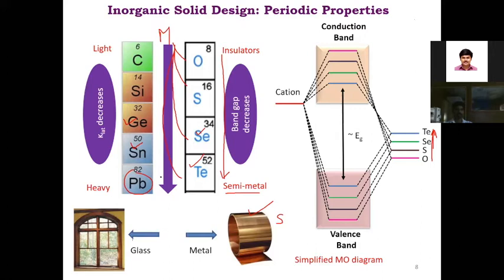So basically, we have to choose heavy metal-based tellurides, selenides, or even to some extent sulfides, or telluride selenides, which have low band gap and heavy mass, that can have low thermal conductivity like glass and high electrical conductivity like metal. So all these three properties converge down the periodic table, and you can make new material if your logic is good. So that is the simple chemistry to design a new material in this field.